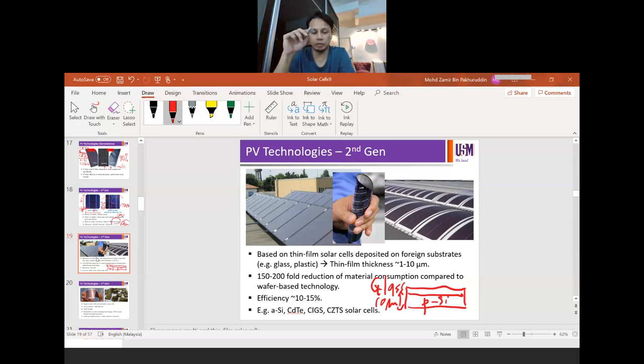We're going to go a little bit deeper when we talk about fabrication process next semester. So I evaporated the silicon in the form of amorphous silicon using electron beam evaporation, 10 micron, and then the amorphous silicon was laser crystallized. So saya guna laser untuk scan the amorphous silicon and melt the amorphous silicon, and at the same time crystallize the amorphous silicon in the form of polycrystalline. So eventually I have a 10 micron thick polycrystalline silicon to be my silicon absorber, right?